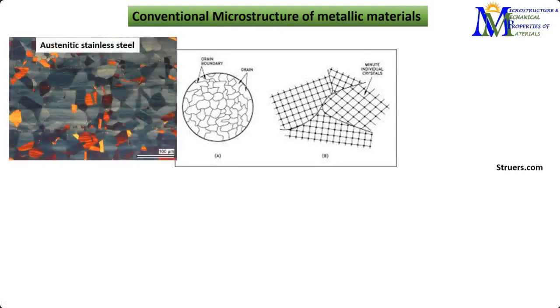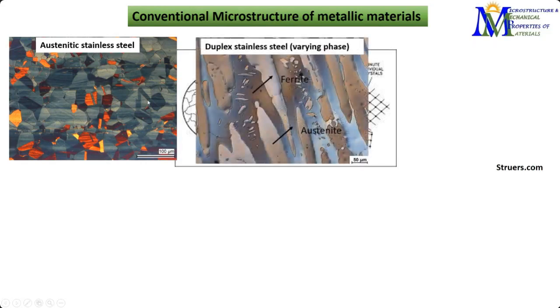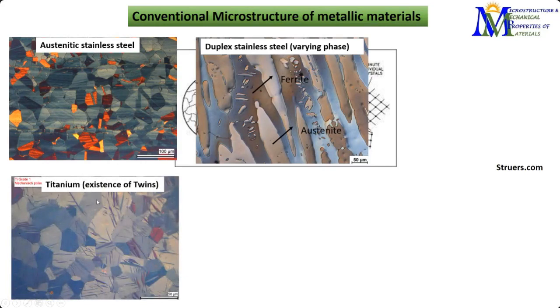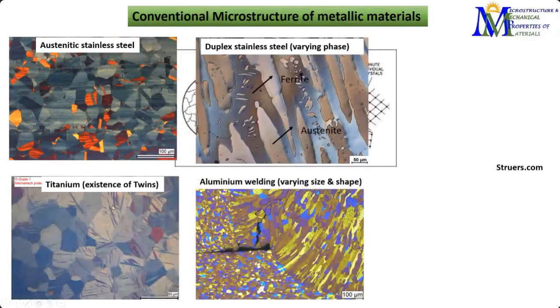So let's see, conventional materials will have a microstructure something like this. This is a real scale microstructure seen in the microscope - this is how it looks. This austenitic stainless steel has grains very much prominent here, and you can see varying phases, the bluish phase versus the grayish phase. These phases, ferrite and austenite, have completely different properties. Then we can have slips and twins that assist deformation, and depending on their presence, we can also have different variation in properties.